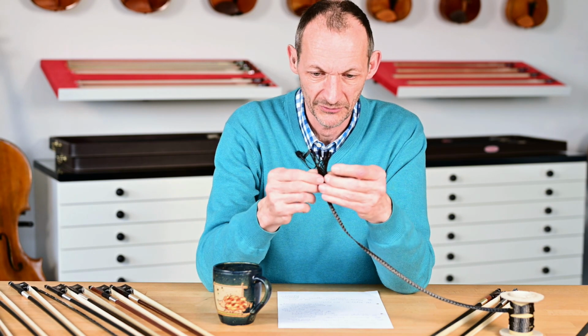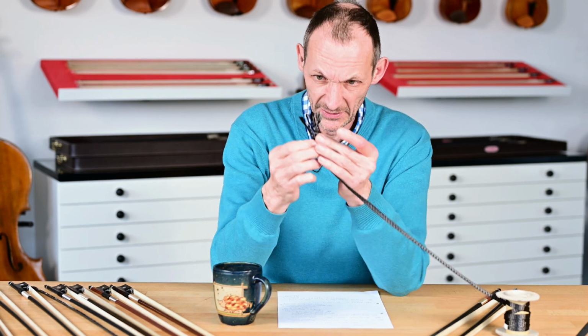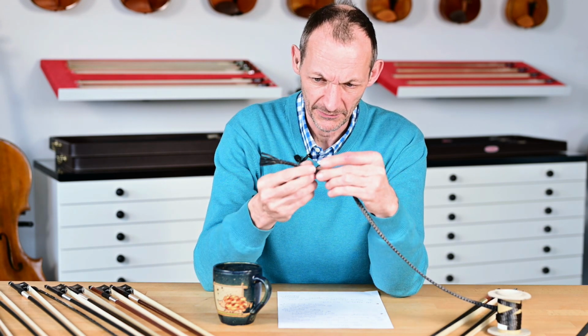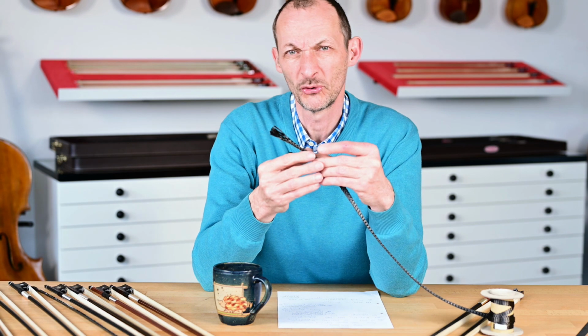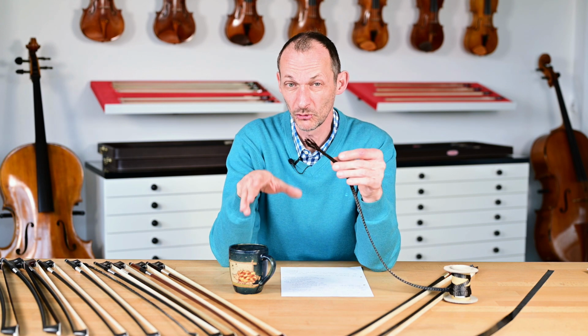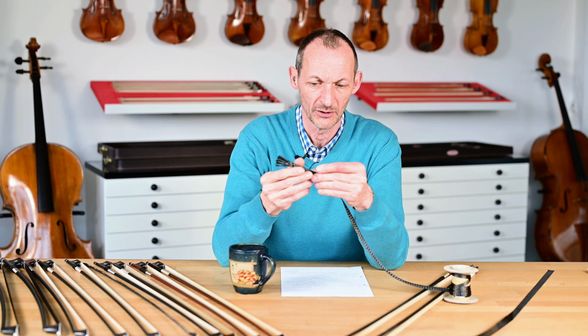Anyways, so here was a very different idea. We could use 3D woven tubes of carbon fiber. You see these strands of carbon fiber. We could make a stick out of these and then inject the resin. And this would make sense if we achieve a resin content of not above 40%. So in the lower end carbon fiber bows, the resin content is like 60%, which is bad. Arcus was 25. So my calculations were, if we get it to 40%, we'll have about the same damping as in high quality Pernambuco. All right, and then we started a process of research and development.